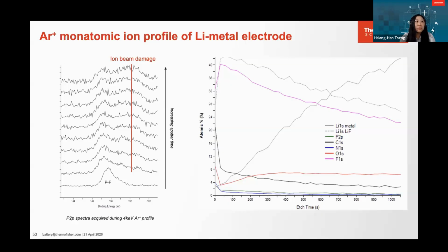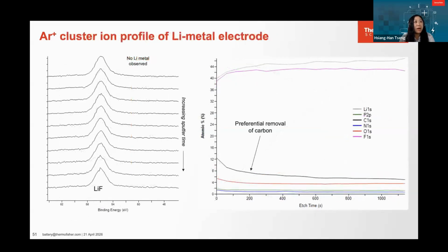In the first place, we try with monatomic argon ions. And here the figure shows you the evolution of phosphorus chemistry. You can immediately notice there is an additional feature that starts emerging just after the first cycle of monatomic ion etching. It's a strong indication that there's some ion beam damage going on to the sample, and it already happened after the first ion exposure. So obviously this is not great.